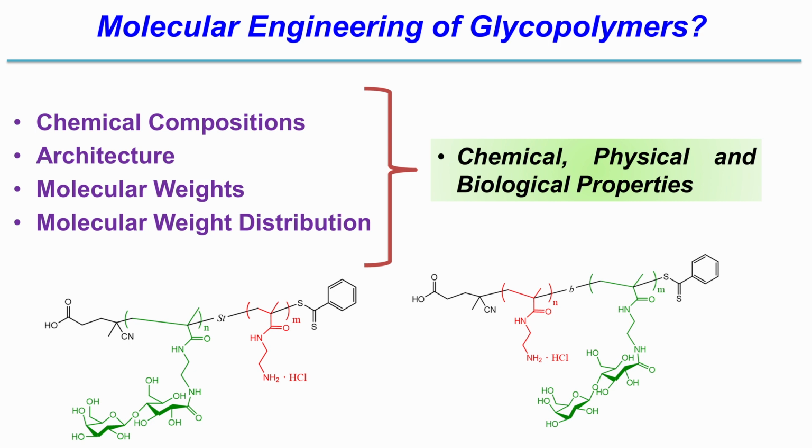With the block copolymer, you tend to have a higher distribution of sugars on the surface. This is important because you want to reduce the cationic charge on the surface. With more cationic charge, what we found is that they are more toxic, and they also tend to aggregate fairly quickly in the presence of serum protein, right?